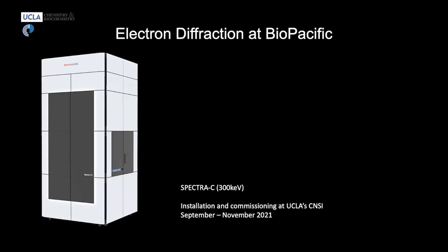So it can be that you're irradiating them, and that's why you're not observing crystallinity, because you're destroying the lattice as you're irradiating it and causing runaway chain reactions or something. It could be that you're damaging an existing lattice as you deposit things onto a grid. Maybe the vacuum is pulling on that lattice and collapsing it in some way, because that lattice depends on ordered gases or solvents or something to maintain its integrity. And so there are a variety of reasons why a pre-existing lattice might collapse. But if you don't have a lattice in the first place, then we're sort of back to square one.